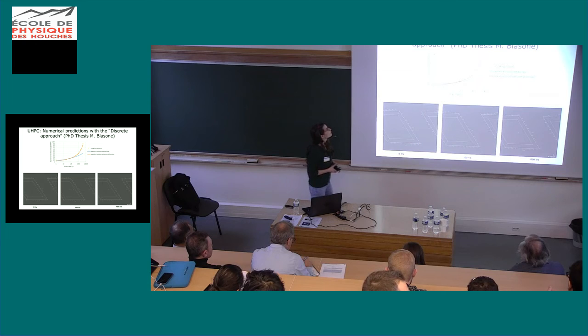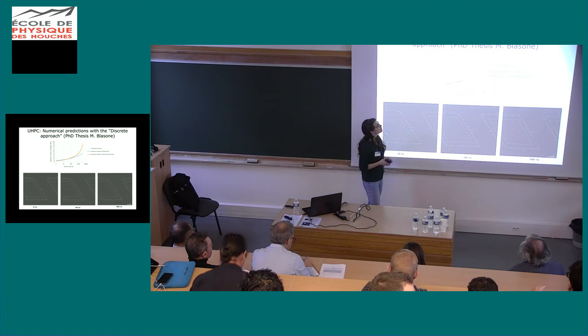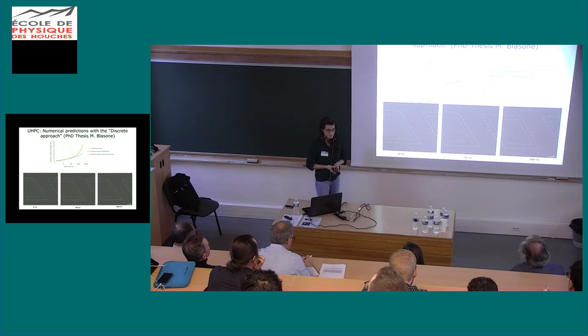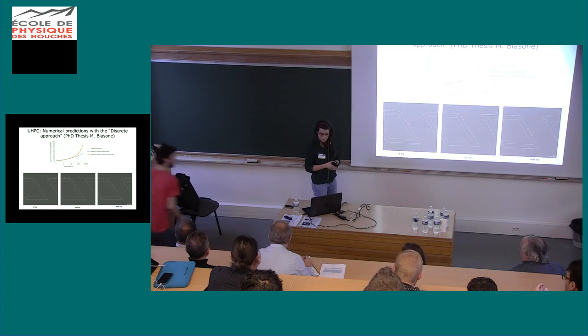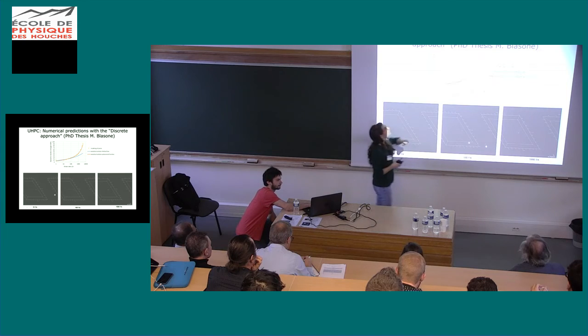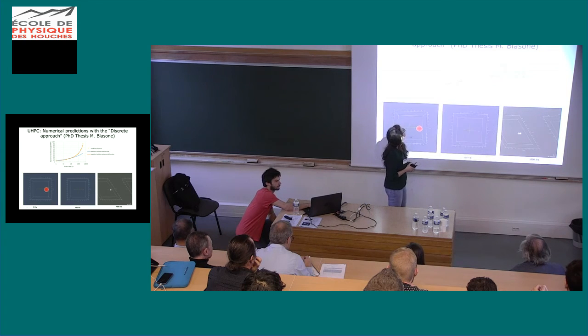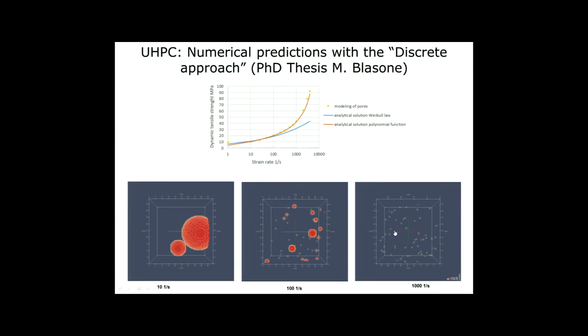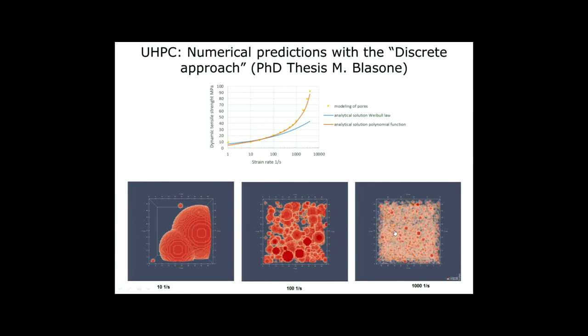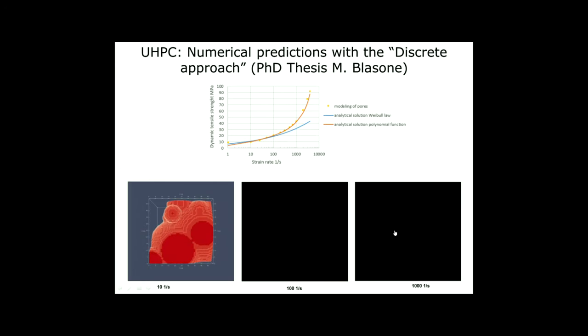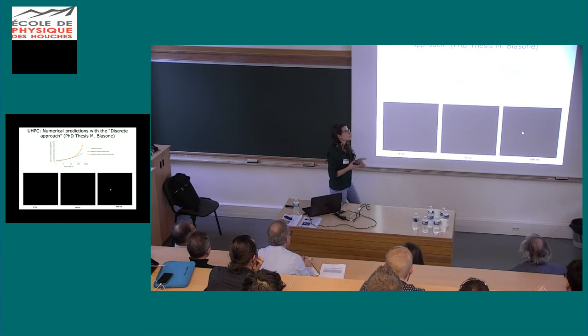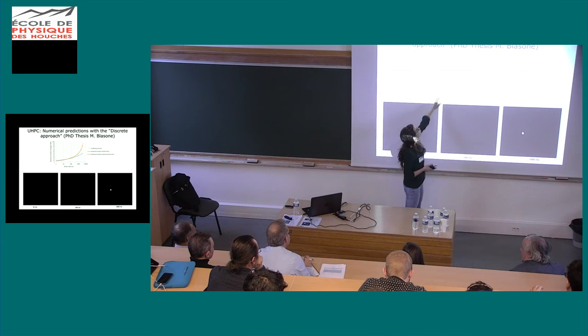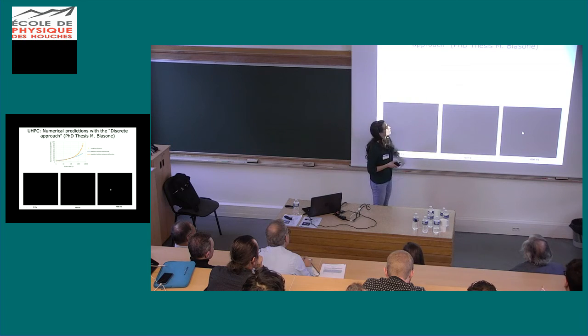So now we can plot together the graph that I showed before with just the analytical formula, and the values that we get from our discrete approach. And we can see that using the discrete approach, we overlap perfectly the analytical solution using the polynomial function. What we can also remark is that for low strain rate, these three approaches are perfectly the same, and they start to diverge at high strain rate.